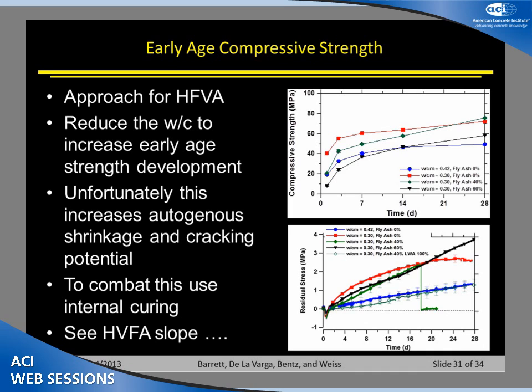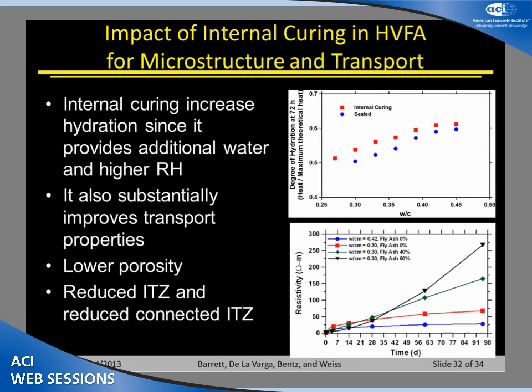However, if you use the high volume fly ash with the internal curing, you can substantially reduce that shrinkage that's taking place and drop back down to a very similar level of stress development inside the deck. So now you've got a 0.3 water to cement ratio system. You've substantially reduced the transport properties, and you've substantially reduced the shrinkage and cracking potential inside of those mixtures.